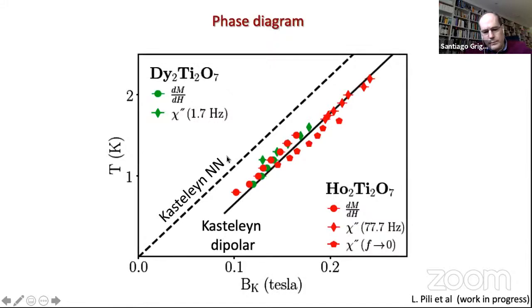But when you do the proper calculation, so you take a Hamiltonian which includes dipolar interactions, and dipolar interactions are important here because we're talking of systems which have magnetic moments of the order of 10 Bohr magnetons, you see that essentially what you're getting is some sort of universal curve that's giving you this Kasteleyn type transition. The one thing to say here is that